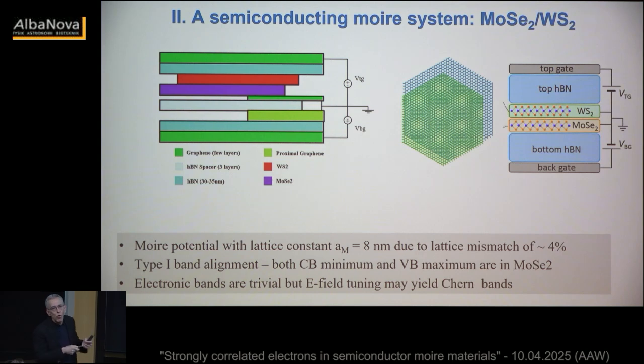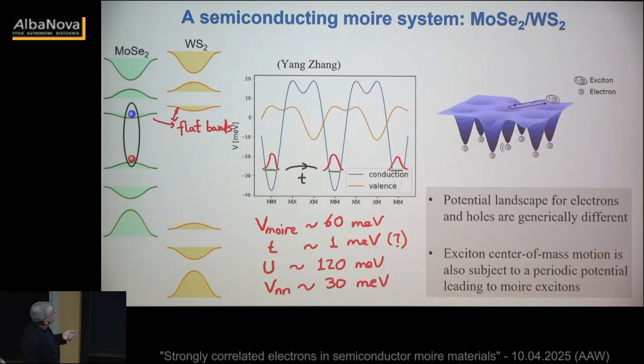The fact that lattice constants are different results in this moire period forming. Now you cannot have very small moire periods. The smallest you can have is 8 nanometers, determined by the lattice structure. Okay, but that's then the structure, molybdenum and tungsten disulfide. This is for excitons a type 1 alignment, so all the optical properties remain the same. It's just that now electrons and excitons in molybdenum are subject to a moire potential. All right. So this is then the sketch. It's a type 1 alignment. As I said, I generate excitons here, and I will be doping electrons in the same way.